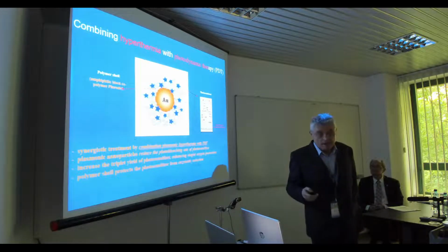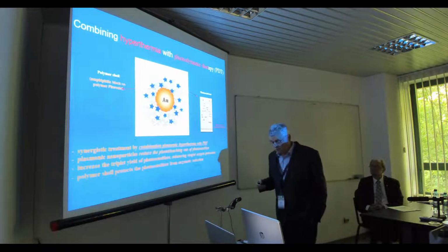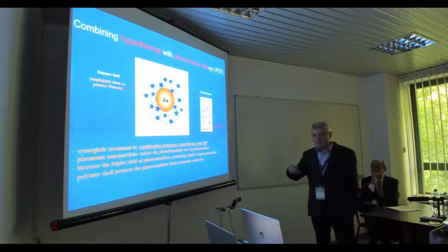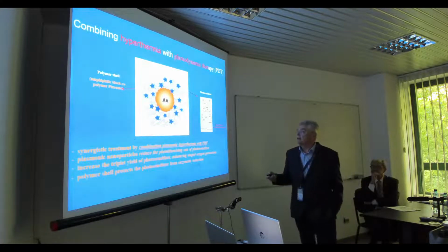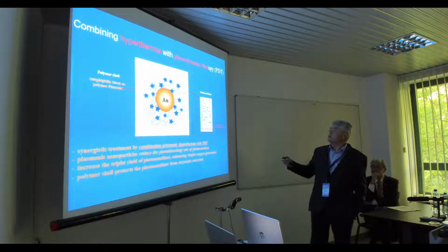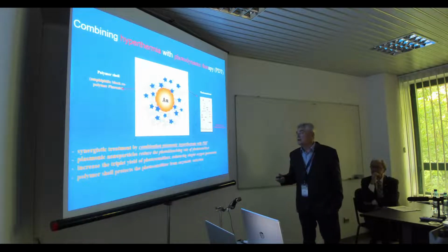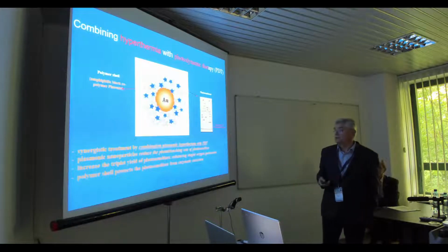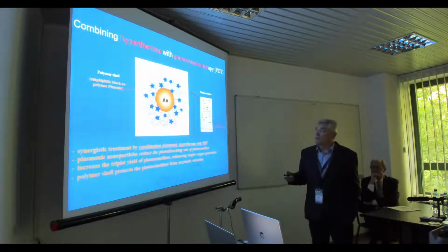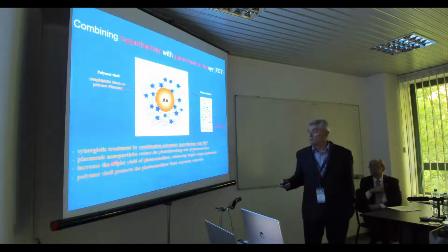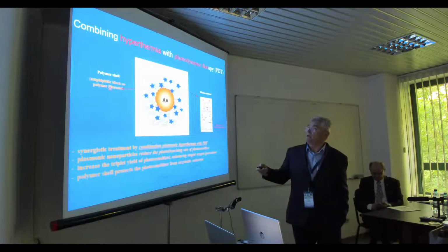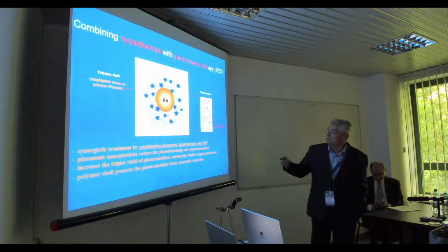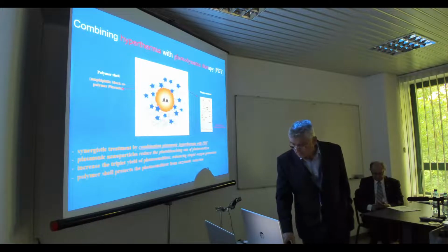Photobleaching can be reduced just because the lifetime of the excited state is shorter, and then you can also improve the transfer to the triplet state, and finally enhance singlet oxygen generation. Also, when you use it with a cell, the polymer here is a pluronic block polymer, which is useful in this kind of study.